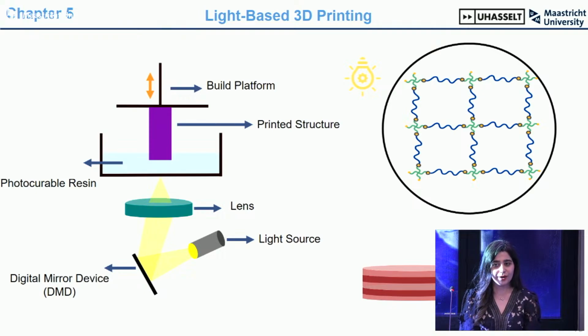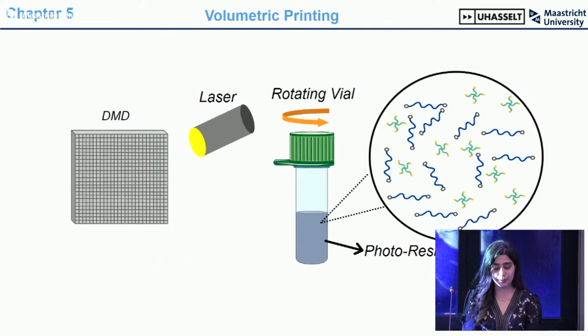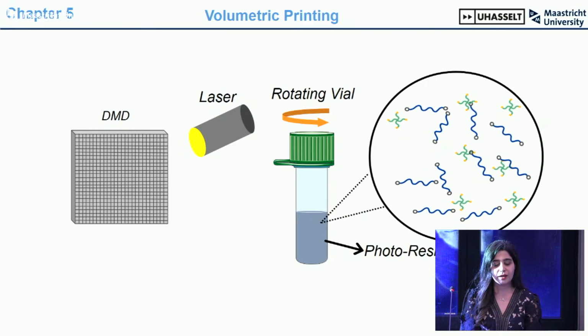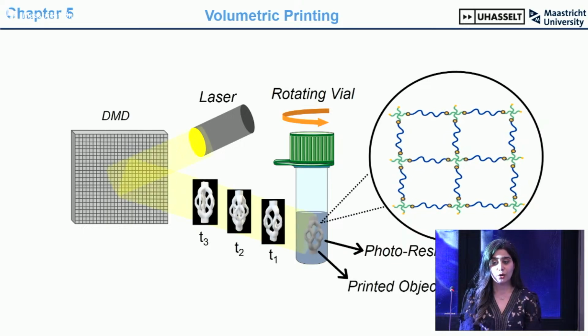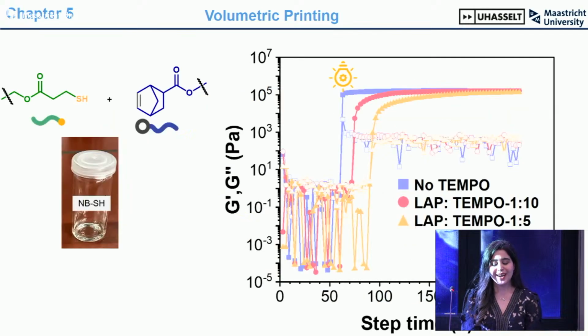To solve this issue of slow layer-by-layer fabrication, there's a new technology, volumetric printing. Here, a rotating vial filled with a photoresin is exposed to a series of dynamically evolving light patterns. When the accumulated energy dose locally exceeds the curing threshold, the entire structure forms at once within the volume of this rotating vial in just seconds. Sounds easy, right? But a lot of optimizations are needed to get it right.